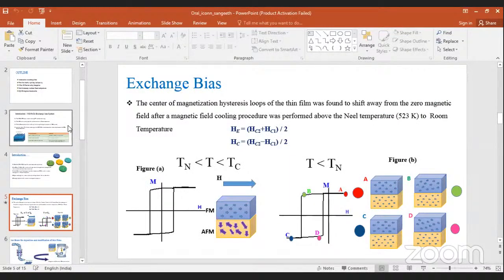Exchange bias is the phenomenon that occurs in an antiferromagnetic-ferromagnetic system when one field cools the system below the Néel temperature. As seen from figure A, the antiferromagnetic ordering is disordered above the Néel temperature. Below the Néel temperature, antiferromagnetic order comes into the picture, and the antiferromagnetic spins just below the ferromagnet align ferromagnetically. When reversing the magnetization, extra force is required to reverse it. This leads to the shift in the hysteresis loop.